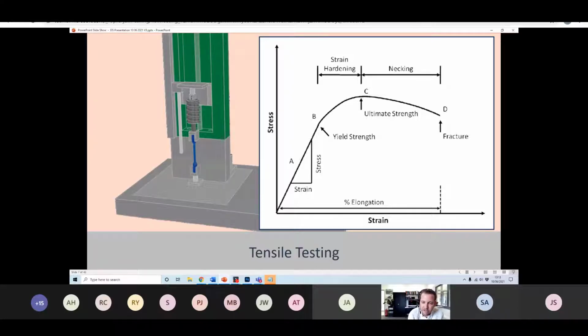And while being stretched, the forces that are needed to stretch it are being continuously monitored. Now, a key feature of this test, which is perhaps a little bit more subtle, is that the stresses and the strains that are developing within the central section of that specimen are, one, uniform, i.e. take the same value, and two, uniaxial, i.e. oriented in one direction along the testing axis. And when you do such a test, a number of features become apparent.